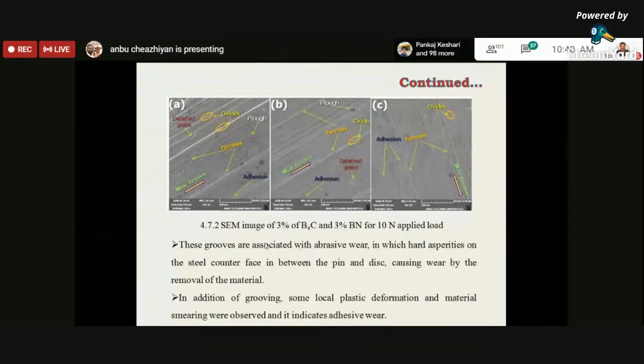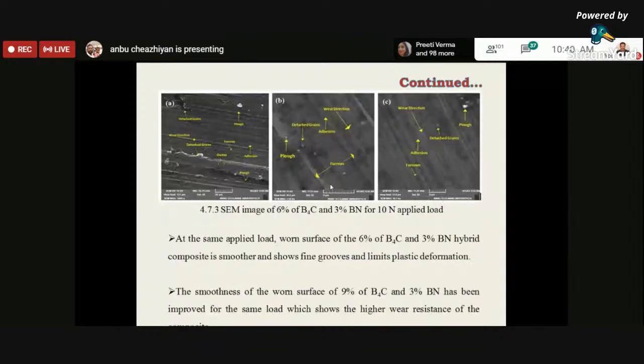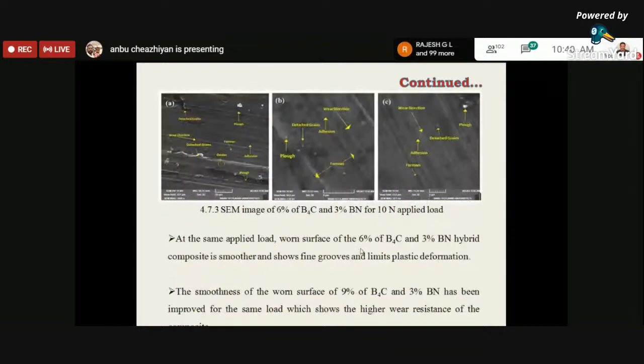In addition to the grooving, some local plastic deformation and material smearing were observed. So here we have 3%, 6%, and 9%. Here I have given for only 10 Newton applied load. At the same applied load, the surface of the 6% boron carbide and 3% boron nitride composite is smoother and shows fine grooves and limits plastic deformation. And in the case of 9%, it is further improved.